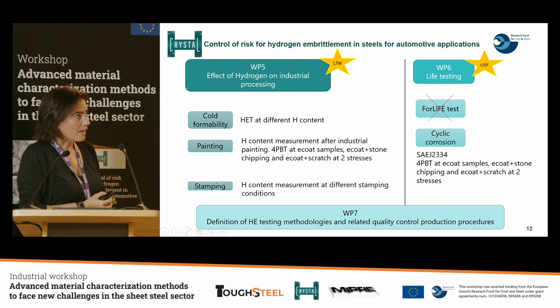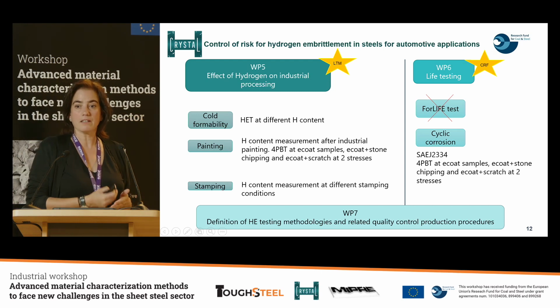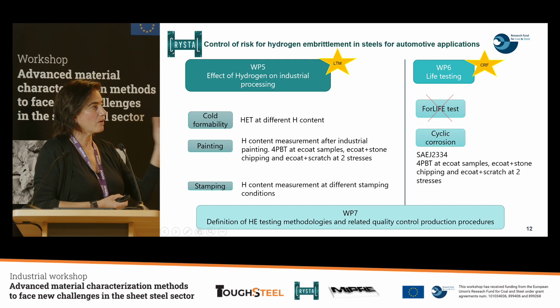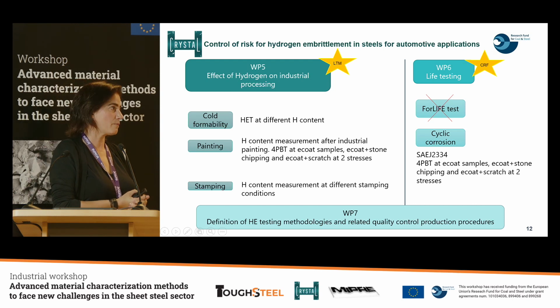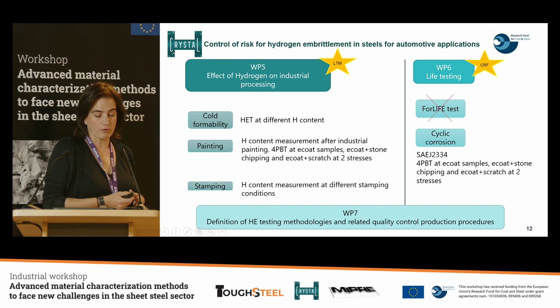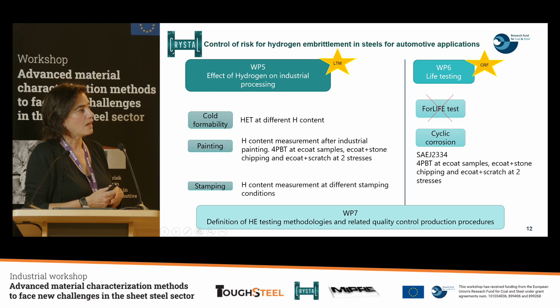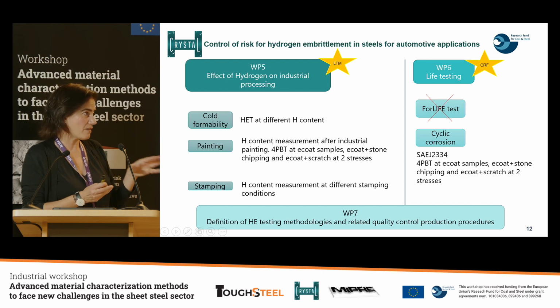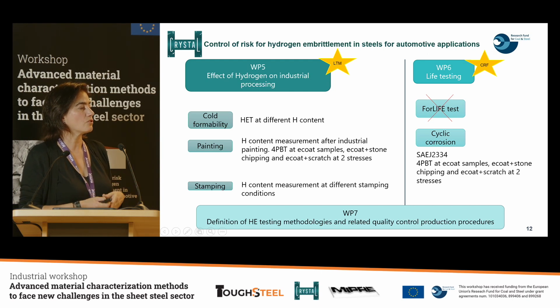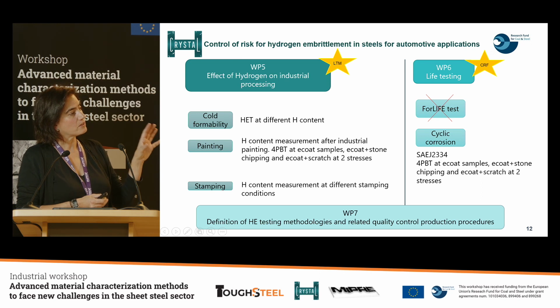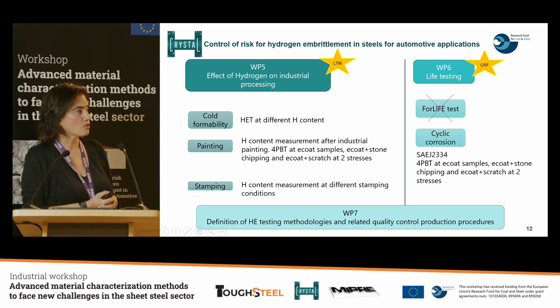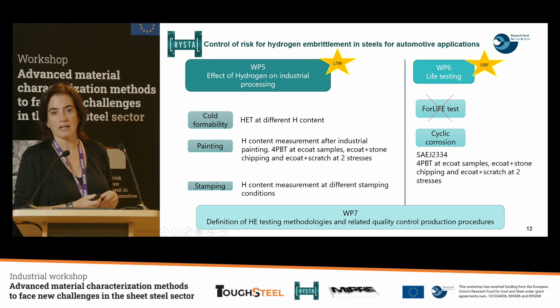So in work package 5, we study the effect of hydrogen, but in real industrial processing. We evaluate the cold formability, performing the hole expansion test at different hydrogen content. Also, we evaluate the effect of painting in different conditions, and we perform a 4-point bending test of different types of painted samples. In basic E-coated samples, E-coated plus stone chipping samples, and E-coated plus scratch samples with 2 different stresses. These samples, we evaluate the hydrogen susceptibility, introducing them in immersion and also in salt spray